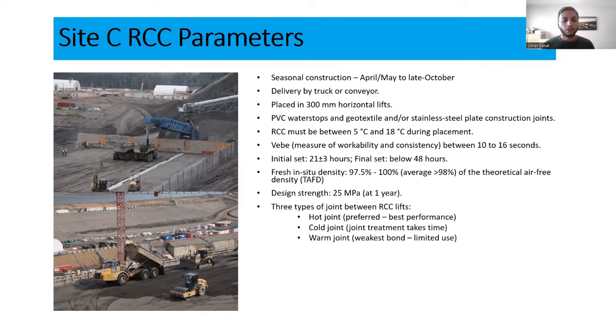And then concrete, as you know, when it's mixed, there is a time for how long the concrete will be live. Within that time, the concrete needs to be worked and then placed in the final location so that it will start to gain its strength. So whenever we are designing concrete, we need to know when our initial set starts and final set happens. Because once the initial set starts, we should not do any more work with the concrete, because if we do that, then we will have porosity in the concrete, which will not be good for our structure.